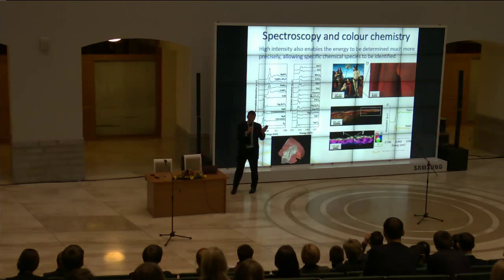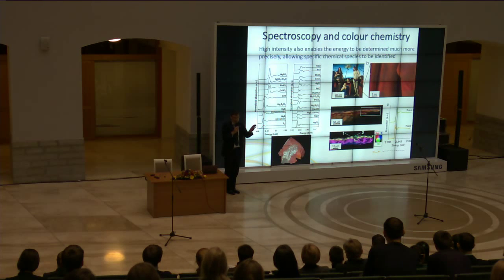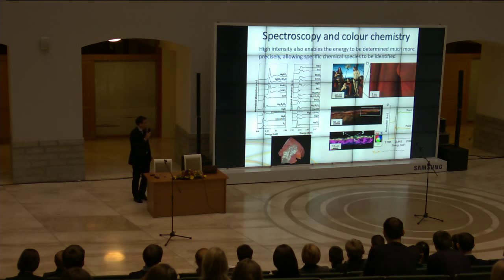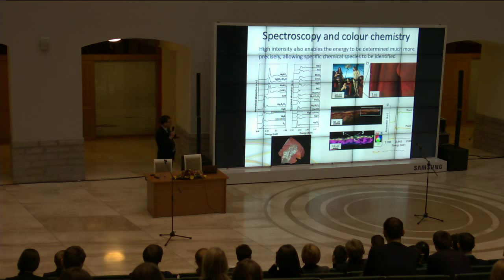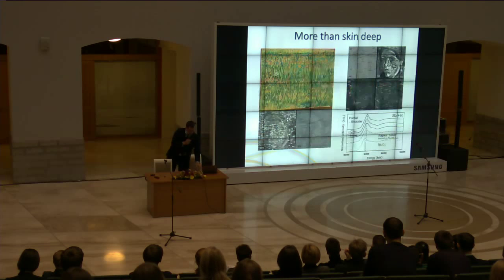The dark bits of the painting, the parts of the painting that should be red and are turning black, are mercury chloride in the region where it was cleaned. And that was because it was cleaned with an agent that contained chlorine, and we now know is harmful to this process. So one of the things that we're doing, I should say instead, this is not actually work done at Diamond. One of the things that we are doing is using very similar techniques to inform people curating pictures about restoration processes and what is harmful and not.